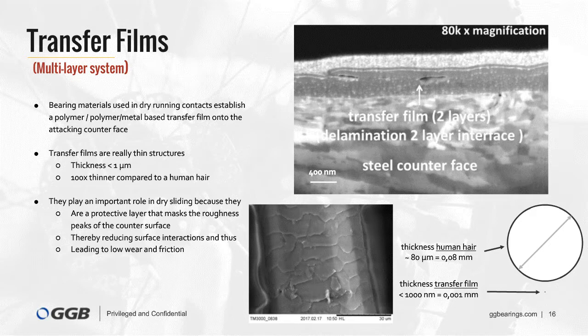Most polymers and composite surfaces are worn by a harder counterface when used in tribotechnical systems. The inevitable wear of these materials when sliding against the harder counterface generates debris. The wear debris can escape from the tribo contact, but normally we hope it stays in the tribological contact and deposits onto the opposing surface.